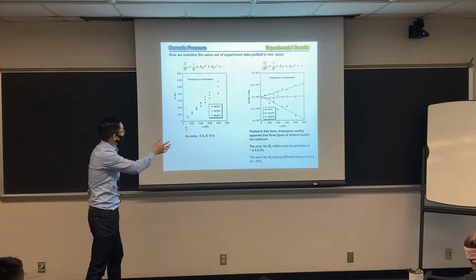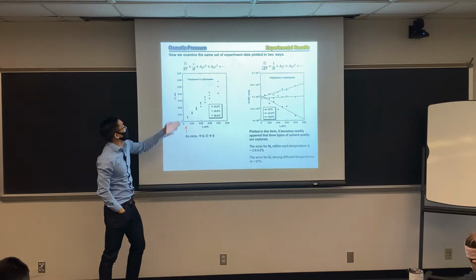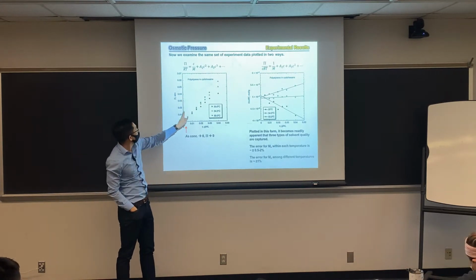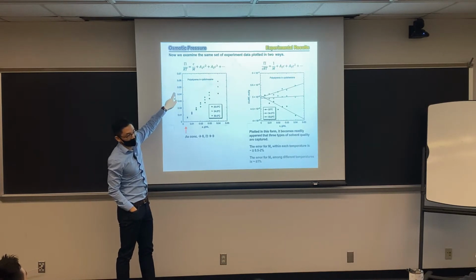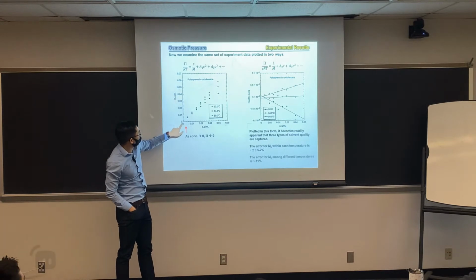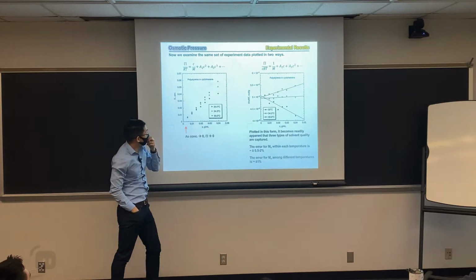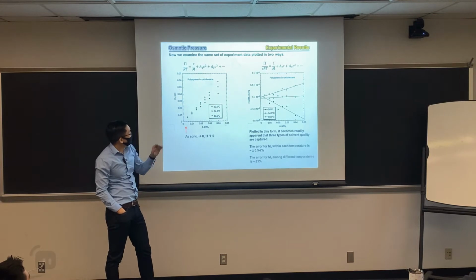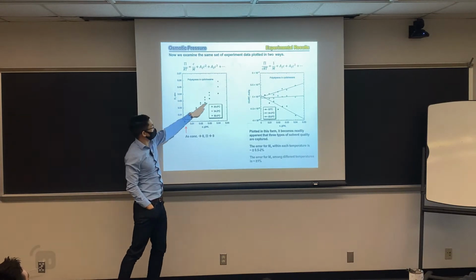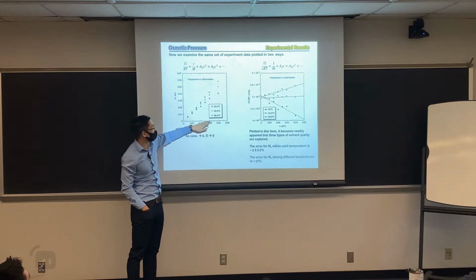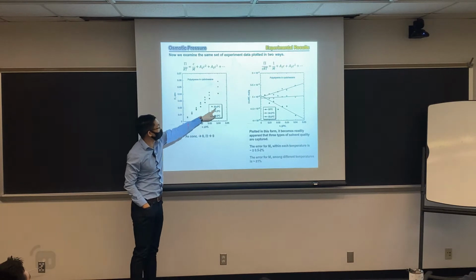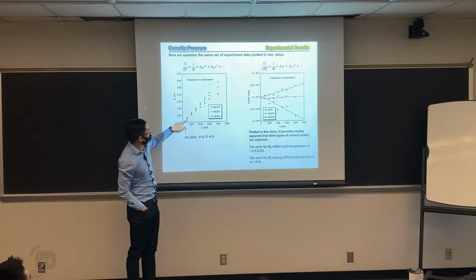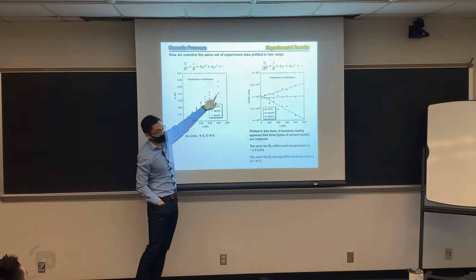Some real data, okay? So this is what people measured in polystyrene cyclohexane. This is measured osmotic pressure in atmosphere, which is a unit of pressure. And this is the concentration of your polymer. There's no question that osmotic pressure is always going to increase with concentration. So in this example, we show that you can measure at different temperatures. Let's look at 20 degrees. You prepare the polymer solution, measure osmotic pressure. Next one, you put it in different vials and measure the pressure.